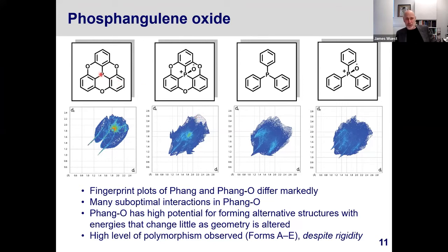This is not characteristic of what happens when you convert a phosphine into a phosphine oxide. For example, if you take triphenylphosphine, one of the known polymorphs of this compound, and the corresponding oxide, the corresponding Hirschfeld plots are relatively similar. So the conclusion from this is that this is a molecule that doesn't have any good choices. This particular offset clamshell pair can adjust itself in slightly different ways without changing the energy substantially. And that's confirmed by the fact that this is a compound that is highly polymorphic.